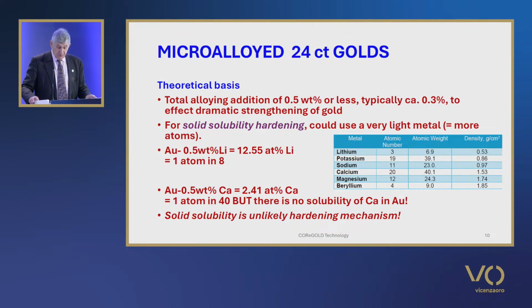We look at the theoretical basis for microalloying. In the development of improved strength 24 karat golds, we're looking at total alloying additions of 0.5% or less, typically 0.3%, and even down to only 0.1% in some instances. And this affects a dramatic strengthening of the gold crystal lattice.